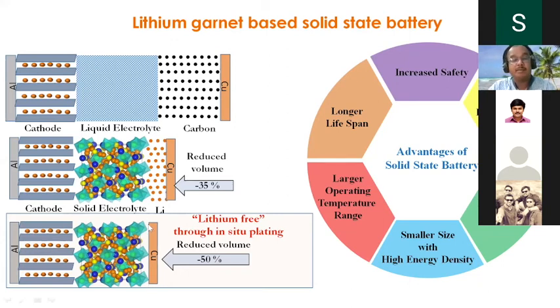Very interestingly, people have observed that it's not vertical; it's perfectly forming a 20 micron or 30 micron metallic layer. Then it goes back to the other side. A shuttling mechanism takes place, and people are able to slowly improve it, because what we require during this plating is that the electrolyte should be stable, there should not be any fracture. Again, during plating, this copper current collector should not be fractured. So people are working hard on how to improve these things.